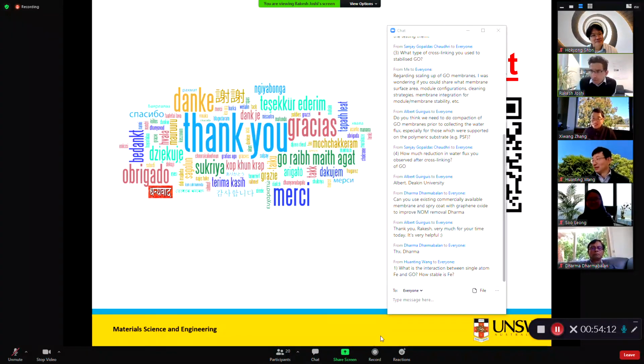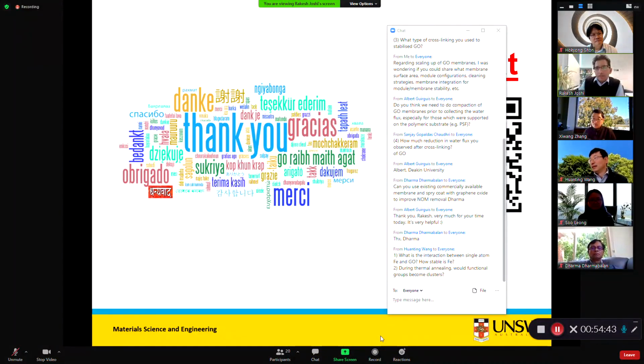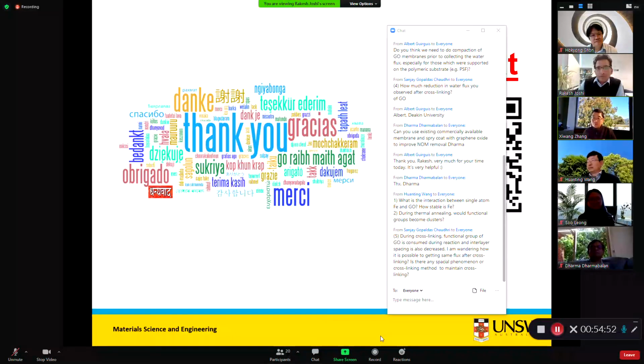So if you use graphene oxide as a support to have a higher water flux and tune the cutoff size, that can be a good strategy. Polymer membranes might not give you a nice cutoff, so we can use graphene oxide to get a cutoff in the size in the membrane for rejection. But I haven't done any work on this yet, because what we do is mainly pure graphene oxide. But for large-scale scale-up, that can be a way for multiple applications, like gas separation with flat membranes.